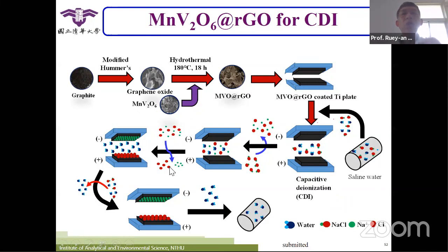You can also try to use some metal oxide inside to do CDI here. Graphene oxide is merged with our MnV2O6 here, using hydrothermal methods to coat it on the surface of a titanium plate, and that forms our material for CDI. So from these ways, you will always see that they can remove ions, especially high concentrations of NaCl, and they can give clean water.